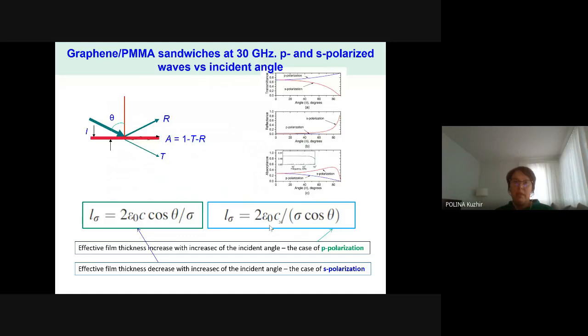Then it's important to understand that this optimal thickness, corresponding to the golden 50% absorption of electromagnetic radiation, is very dependent on the polarization of the incident radiation. For S polarization, this optimal thickness is proportional to the cosine of the incidence angle, whereas for P polarization, it's inversely proportional to the cosine of the incidence angle. This means that for S polarization, we could achieve 50% absorption of electromagnetic radiation with an almost invisible thickness.